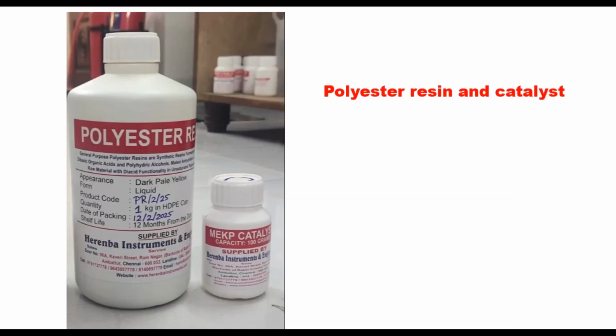If you are using adhesive material as suggested in ASTM D3319, in place of cement sand paste, then take the polyester resin and catalyst having a pot life of 20 to 30 minutes and curing time of 3 to 6 hours. The bonding agent should be quite viscous and should not flow completely around the aggregate particles, and they should not become part of the surface of the test specimen.